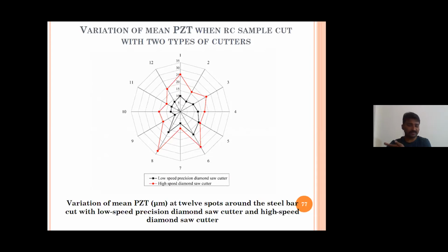To cut the sample, I have to cut it. There is some amount of damage, but if you use low speed diamond saw cutter, the damage can be reduced to a certain extent. So from this we have concluded that you have to use a low speed diamond saw cutter for cutting the steel or reinforced concrete samples.